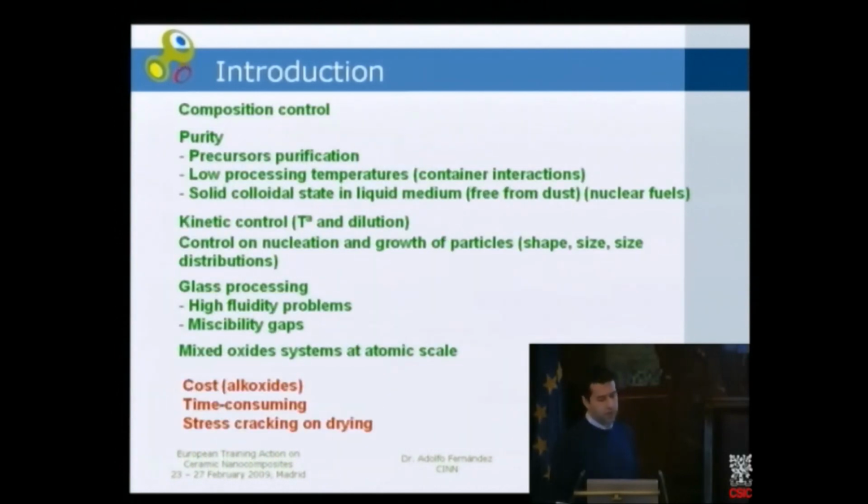The main advantages of using the sol-gel method is principally the purity, because it's the only way to obtain really completely pure materials. And this purity could be even improved by using precursor purification. And as the subsequent temperatures for processing these materials are relatively low, container interactions are avoided. As it's a solid colloidal state, but it's using a liquid medium, the product is free from dust.